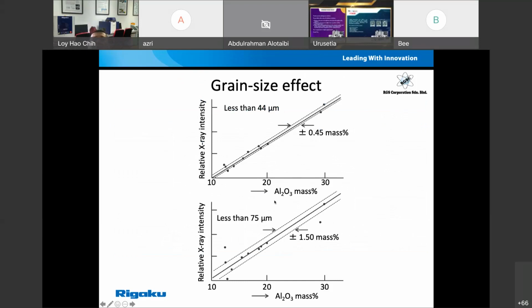Okay. So this is an example of the grain size effect. This is the same sample with different grain sizes. You can see that on the x-axis is the alumina concentration, from 10 to 30%. On the y-axis is the relative X-ray intensity. For the same sample with a smaller grain size, the fluctuation range is very small, about 0.45% of the mass percentage.